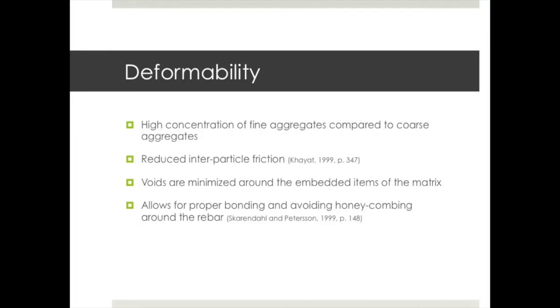Khayat defines deformability as the ability of the concrete to undergo a change in its shape under its own weight, even in the vicinity of obstacles that can interfere with its flow. SCC is deformable because of its reduced interparticle friction by using a higher concentration of fine aggregates compared to coarse aggregate. Because of the deformability of SCC, the voids are minimized around the embedded items of the matrix, allowing for proper bonding and avoiding honeycombing around the rebar.